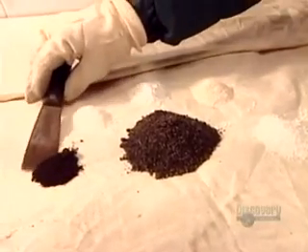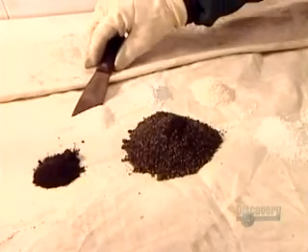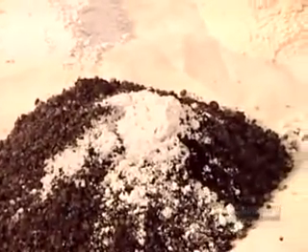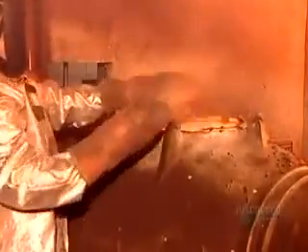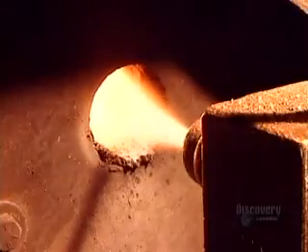To smelt it into bars, they first have to mix several chemicals: manganese dioxide, fluorite, silica flour, borax, and sodium nitrate. This chemical mix, called flux, will separate the gold from the impurities. They pour it into the smelter, whose temperature is a fiery 1600 degrees Celsius.